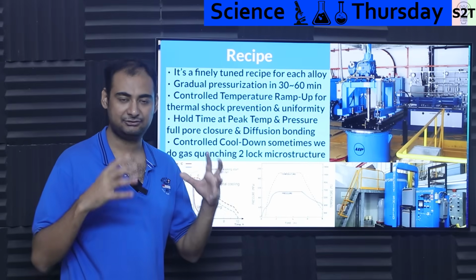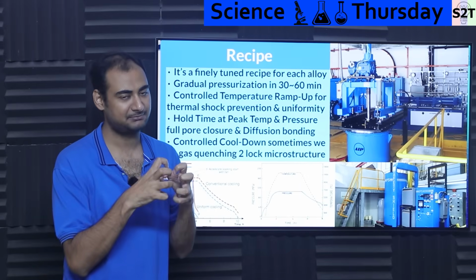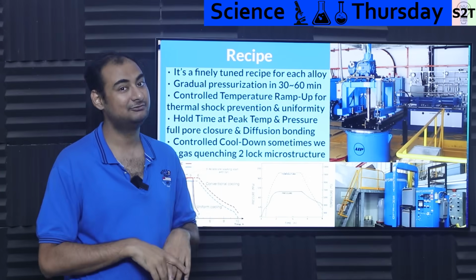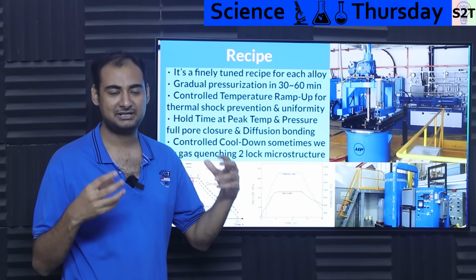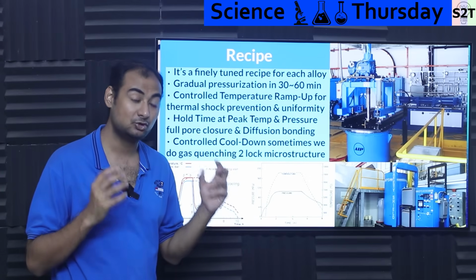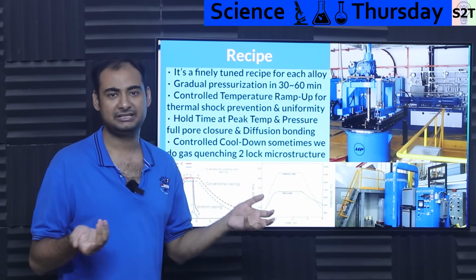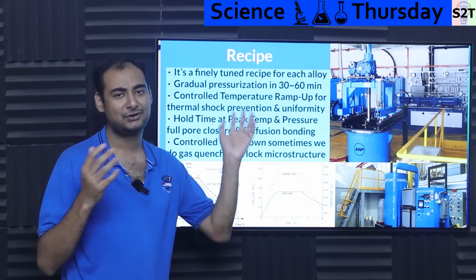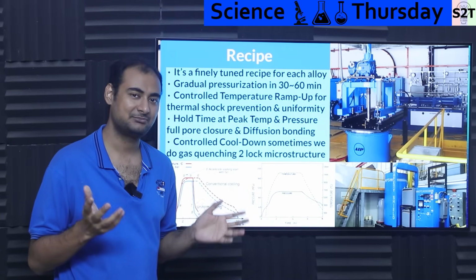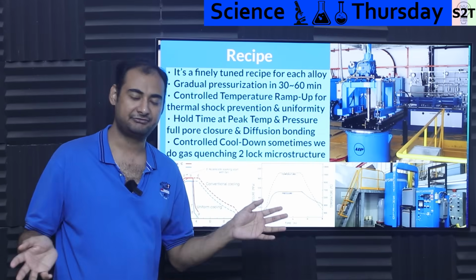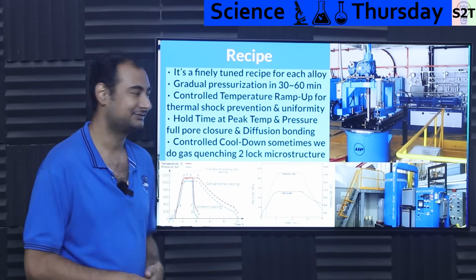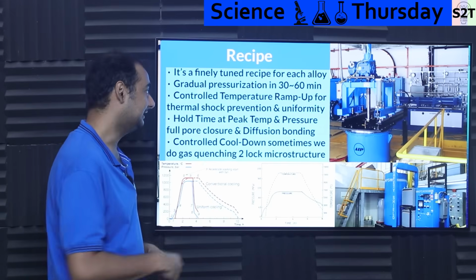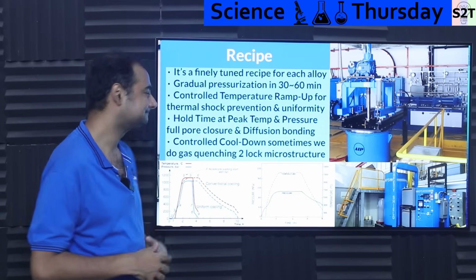And be mindful, if you have very high porosity, you can shrink the part. So that has to be calculated forwards. Jet engine turbine blades are generally very high density, very low porosity anyway. They only have, let's say, 10% void. 10% void you can send into this, it will not change the shape or structure. But if it's like 50% void, yeah, then it will shrink. So you have to be mindful of that. And again, the recipe accounts for all of that.